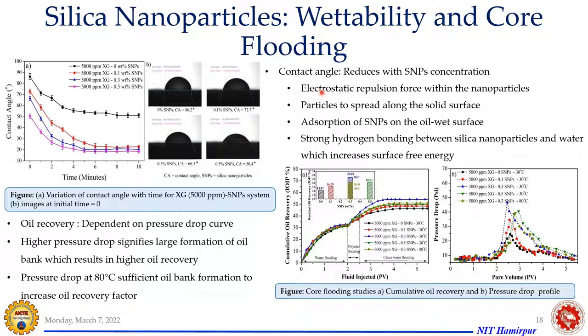So when we have nanoparticles, they have a high electrostatic repulsion force within the nanoparticle film. This electrostatic repulsion force causes the particles to spread along the surface, because of which there is adsorption of nanoparticles at the oil-water interface. And then you can see the strong hydrogen bonding between nanoparticles and water, which increases the surface free energy. Because of all these mechanisms, you can see the modification of the surface from hydrophobic towards hydrophilic is achieved, and the oil is being released from the rock surface.